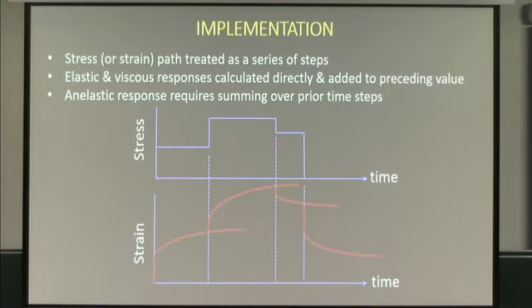So a couple of quick applications. You can take the model and formulate it for a series of step changes in load or step changes in strain. And in the former, each load step, again, this is just completely arbitrary, but just to show you the response. The way you would model this is you take the full model, elastic, anelastic, and viscous components. For each step, you would say, all right, here's the step, that's an elastic response, and then in time, you'll have this delayed elastic effect and creep from these other mechanisms. So each step, you would keep track of this tapering off in deformation.